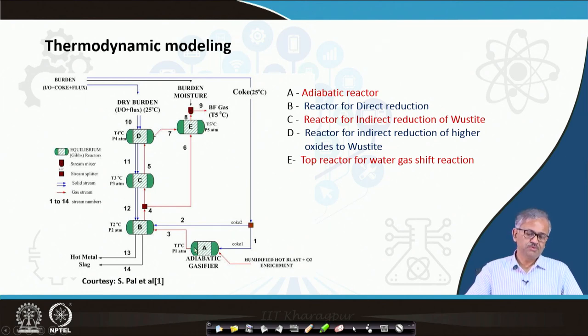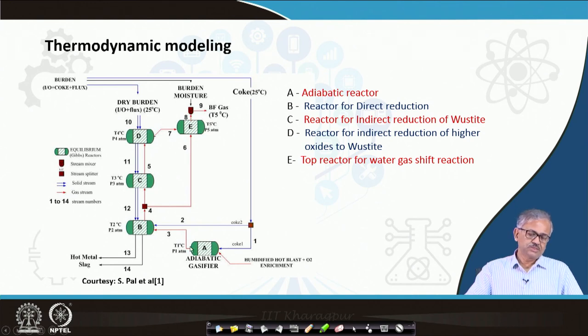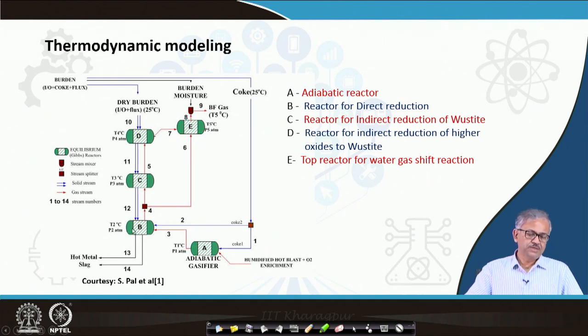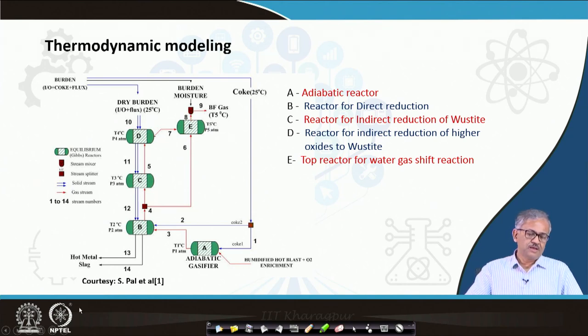The final composition will obviously be CO gas, and since air blast is used, nitrogen will also be there. This CO and nitrogen will enter into reactor B. Reactor B is called the reactor for direct reduction — it is a high-temperature reactor.